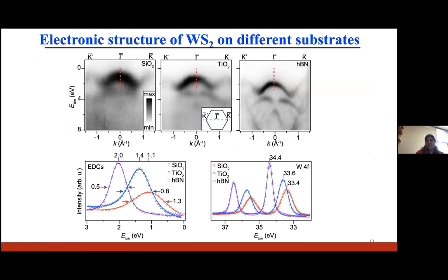And so here I'm showing just a comparison of the single layer WS2 on 3 different substrates. Here's the dispersion along the K prime gamma K direction for single layer WS2 on silicon oxide substrate. In the middle, we have it on the titanium oxide substrate, and on the right, I have it on the HBN. And as you can clearly see, we have the sharpest band when we have WS2 on HBN.